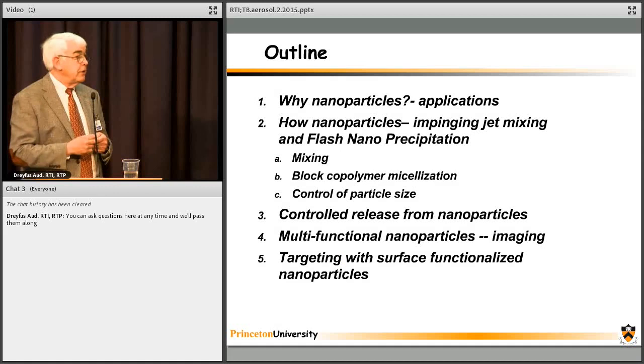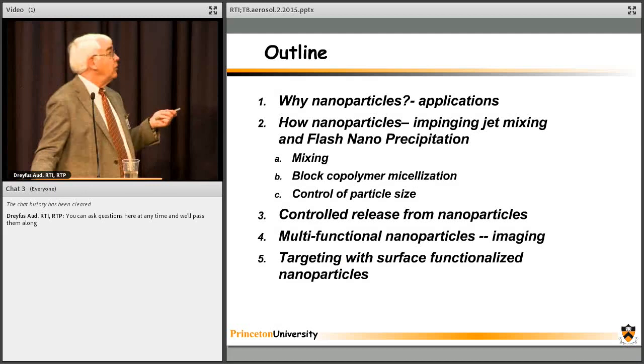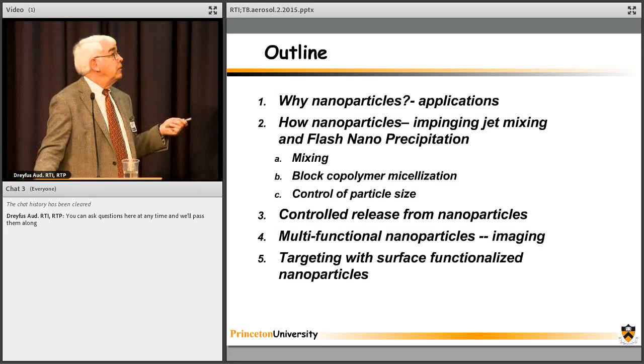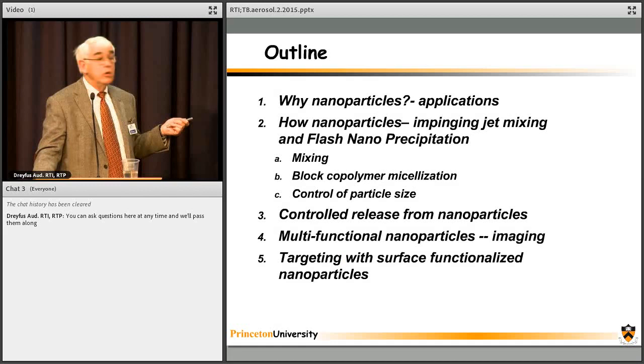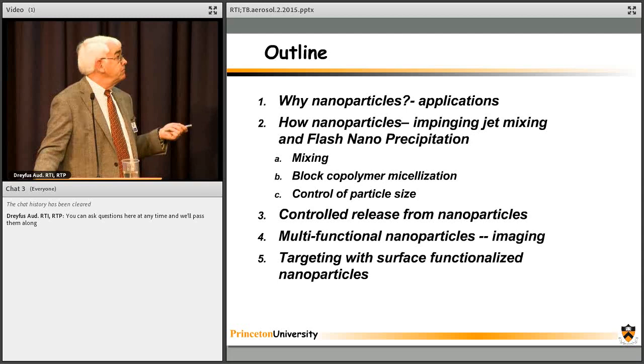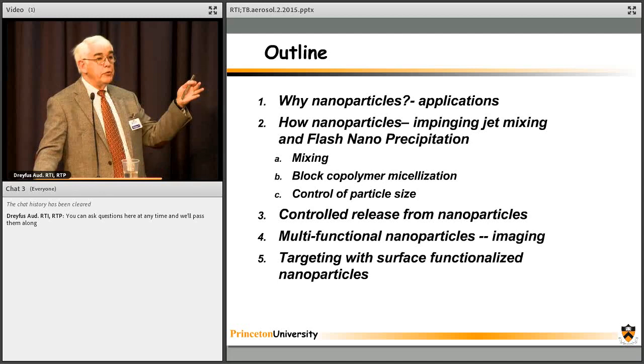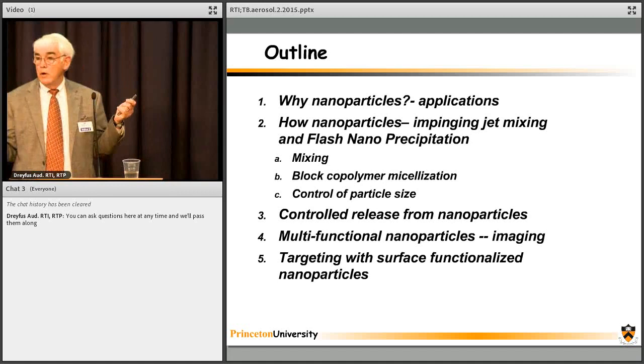Okay, so thank you for your time. So here's what we've covered. We talked about why we want to make nanoparticles, our block copolymer-directed rapid precipitation. Crucial there is the right micromixing and the engineering behind that. We control particle size easily by controlling supersaturation. And then we talked about release, where we can now tune release from a few minutes to 30 days, depending on the conjugation chemistry. You just go to your organic chemistry book and find conjugates that release at the right rates, so you can tune your release rate over that period of time.